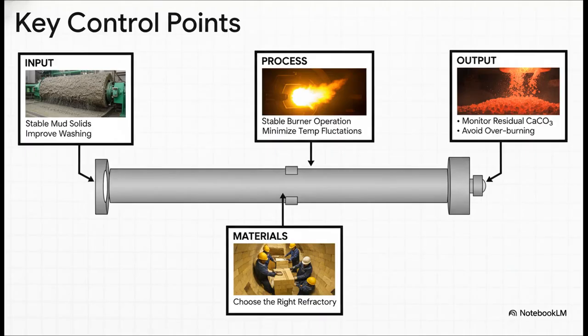So when you boil it all down, real control comes from just a few key areas. First, on the input side, stabilize your mud solids and get your washing as good as it can possibly be to control that sodium. For the process itself, a stable burner is absolutely non-negotiable. You have to minimize those temperature swings. On the output, you've got to monitor your residual CaCO3 to make sure you're not overburning the lime, because that just eats your refractory for lunch. And finally, material selection. You have to have the right brick in the right zone.